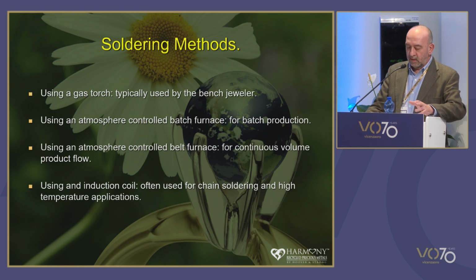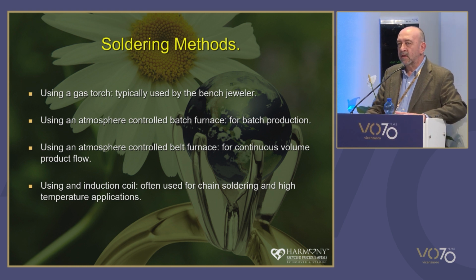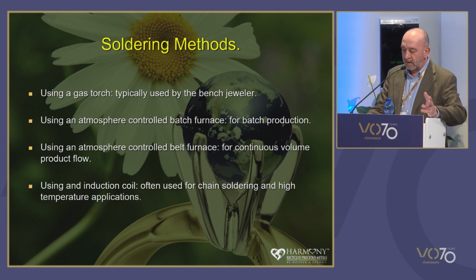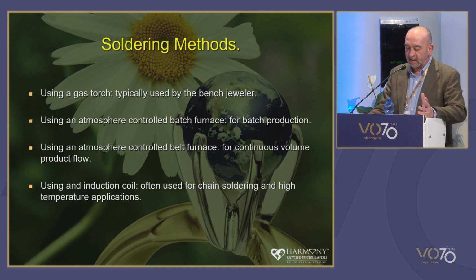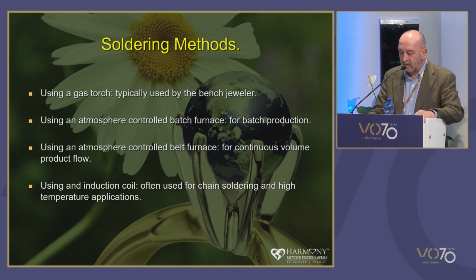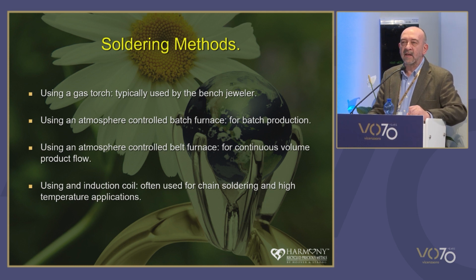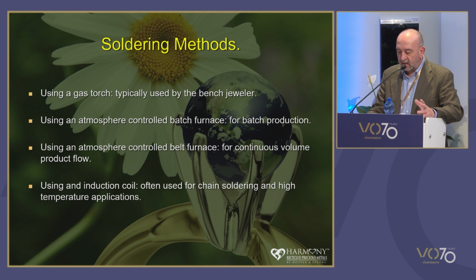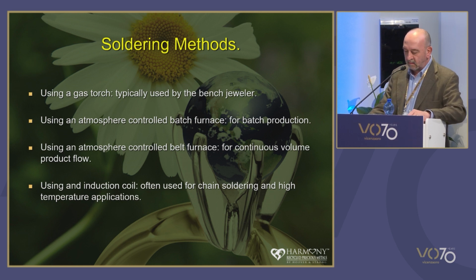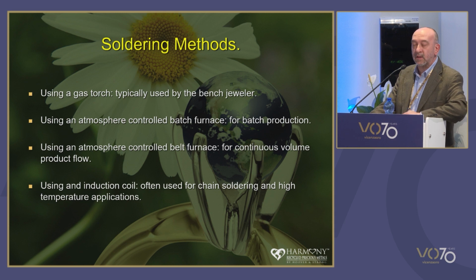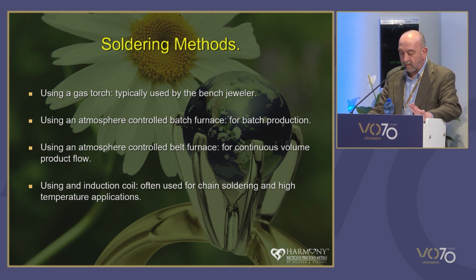So when torch soldering the joint, the area must be heated and not the solder. Everybody knows this who's a jeweler, but it's worth reiterating. Solders always flow to the area of greatest heat and not away from it, so that's how you do it. Time at temperature should be kept to a minimum to prevent excess flow, excessive diffusion into the parent metal, or any volatilization of low melting point constituents from the solder, which can lead to porous joints. Both torch and furnace methods can use solder paste, but we're not going to go into these for this study. They're an entirely different study that could be looked at some point.